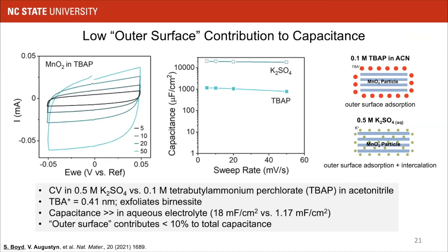One of the things we wanted to understand is whether most of this capacitance was just coming from outer surface processes, ion adsorption at the outer surface of this material. So what we did is this experiment that we learned from Deborah's research, which is to take the birnessite and cycle it in an aqueous electrolyte that contained a relatively small cation like potassium, as well as in a non-aqueous electrolyte that contained a bulky cation like tetrabutylammonium, and compare the capacitive response. Tetrabutylammonium has an ionic radius of 0.41 nanometers. It's actually used to exfoliate birnessite.